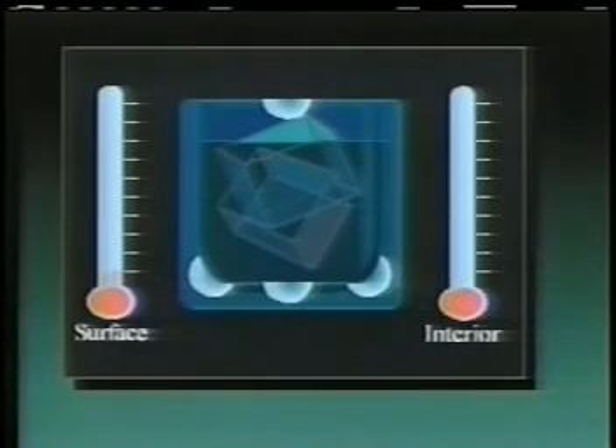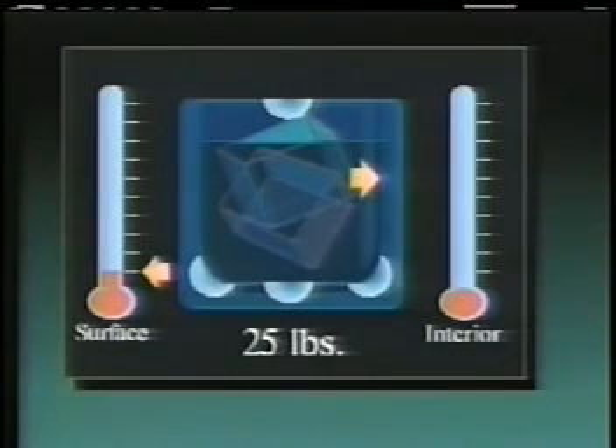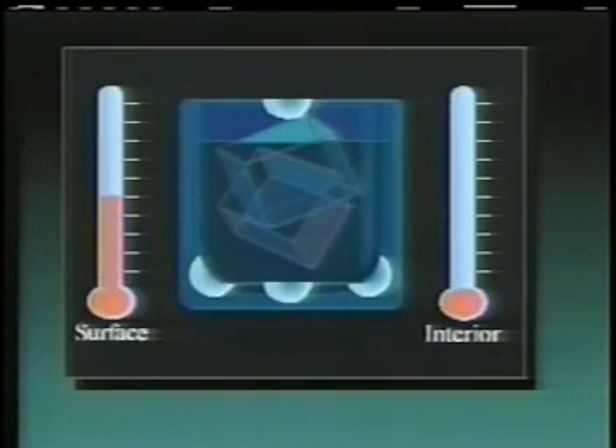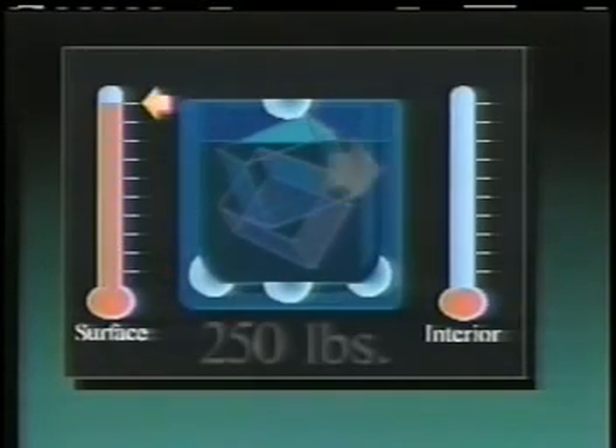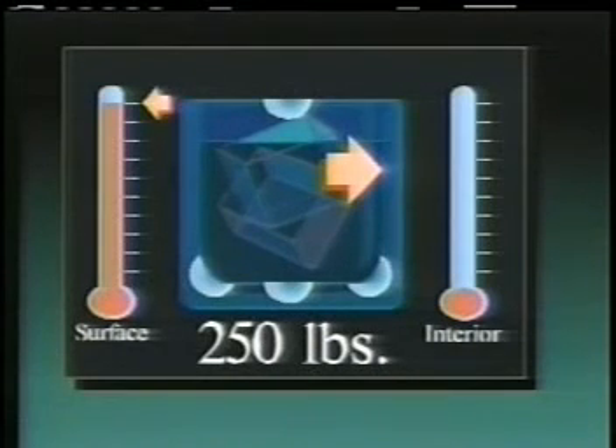In fact, for every degree Fahrenheit that the surface of the glass is different from the interior, the thermal stress on the surface is approximately 25 pounds per square inch. Thus, with a fast 10-degree change, the stress on the surface is 250 pounds per square inch. You begin to see why the surface flaws we discussed can take such a devastating toll on glass.